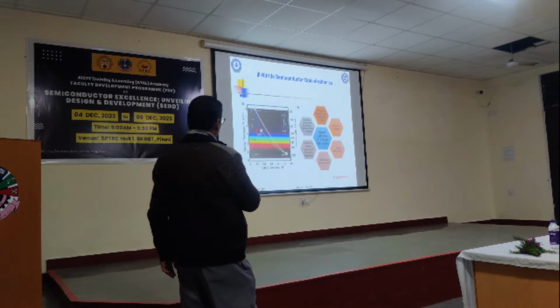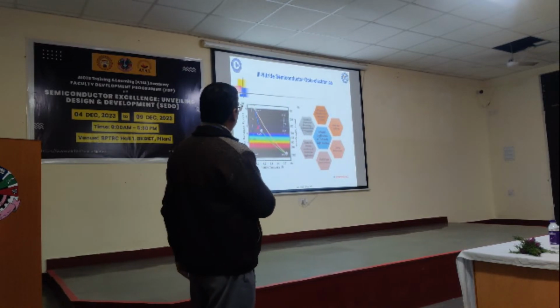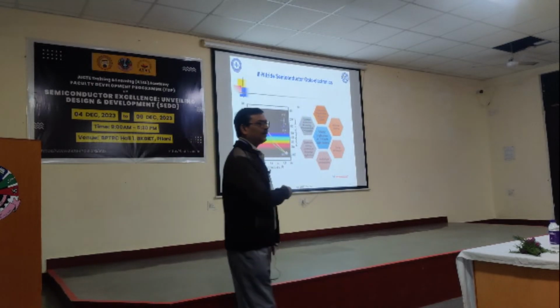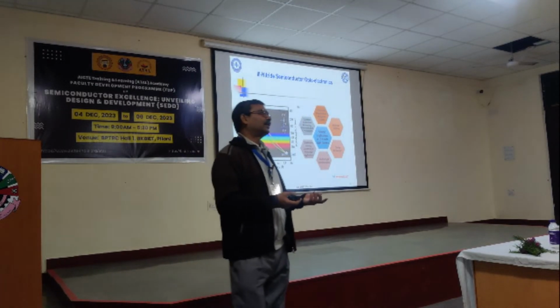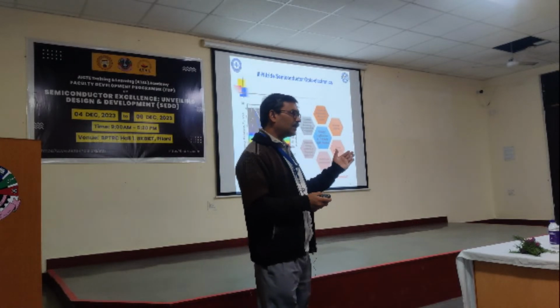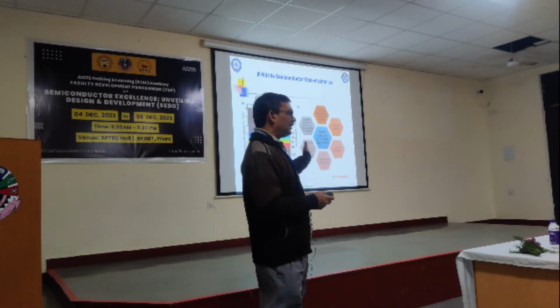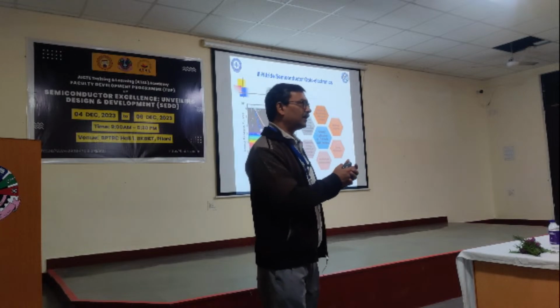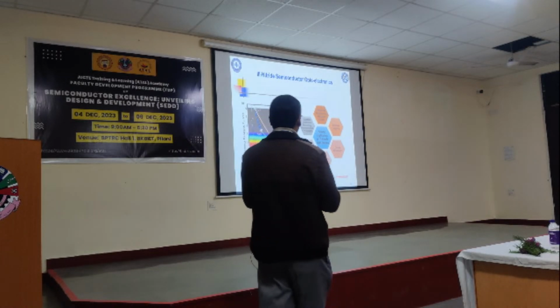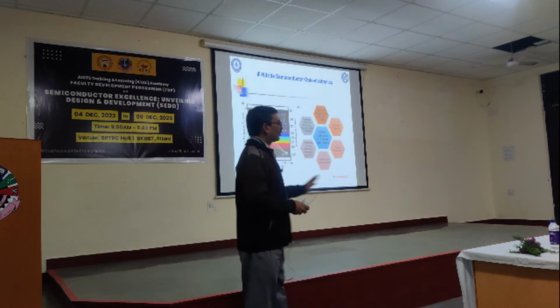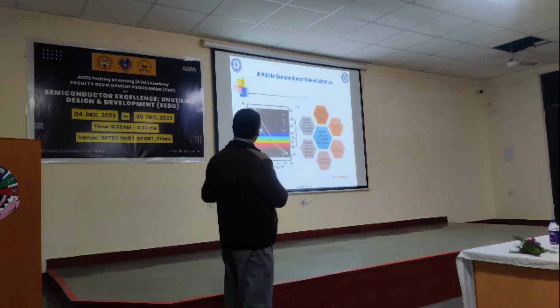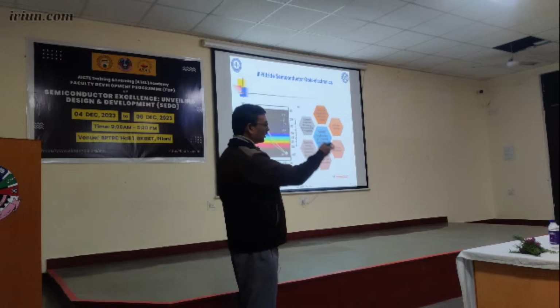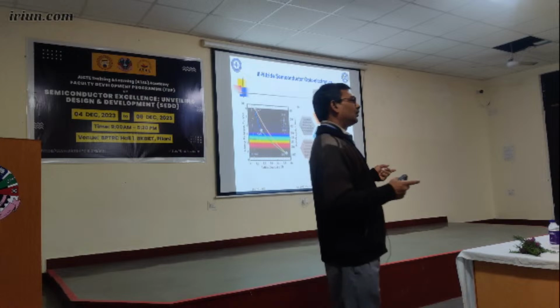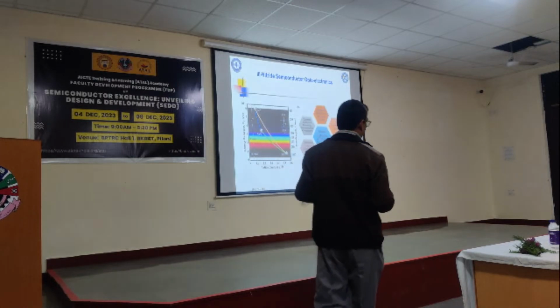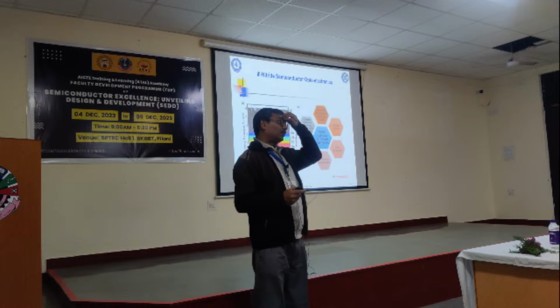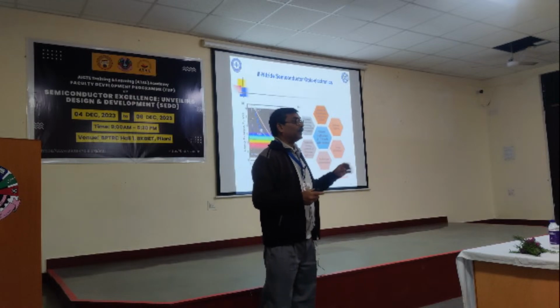If the band gap is very high, from the band gap itself we can estimate the emission wavelength if we want to make, suppose, an LED. We are driving it by giving an electrical signal, and we are getting the optical signal. So corresponding to a band gap of 6 electron volts, we can estimate it as 1.24 divided by Eg, and it will be around the UV range.